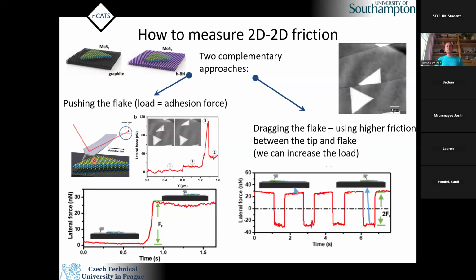And then when you want to increase the load, you would say, okay, but there is no load, there is just adhesion. But we said, okay, we can do another thing. We can touch the surface, touch the flake somewhere in the middle, and then drag it. Because friction between the tip and flake is typically higher than between the flake and the substrate, which is another, bigger flake, your tip will stick on the surface, and you can really move it back and forth.